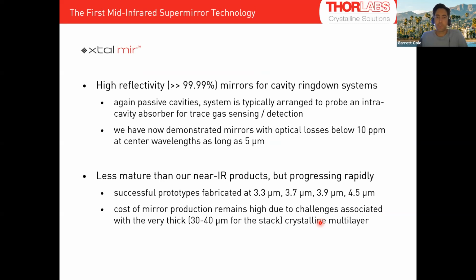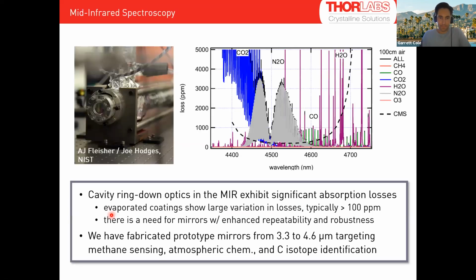Here the goal is to push to similar levels of performance to these near infrared ion beam sputtered optics, but in the mid IR for the first time. This is less mature than our near infrared products. I'll jump to the second bullet point there, but we've been making rapid progress. We've made prototype mirrors at 3.3, 3.7, 3.9, now 4.5 to 4.6 microns. These are very challenging to make because the crystal growth is very thick, and defect densities tend to get high, and so on.